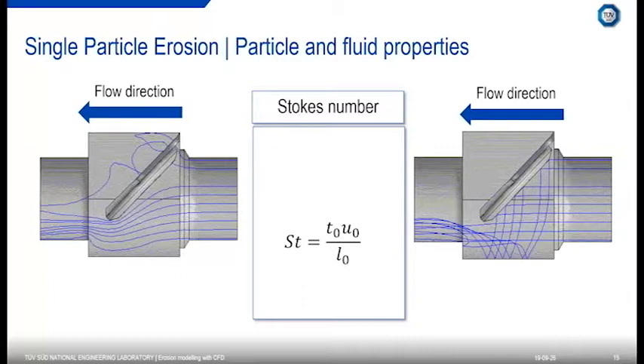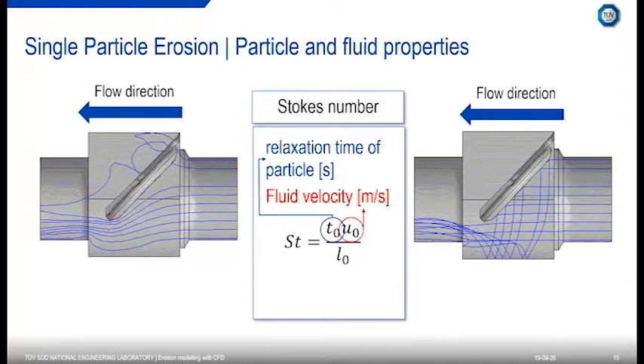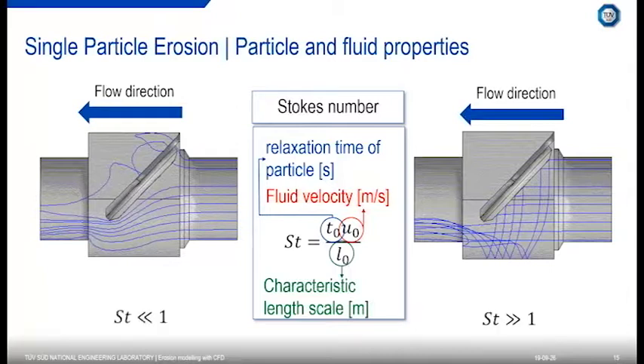So it's defined as the ratio of the characteristic time of the particle, given by the relaxation time, its fluid velocity, against its characteristic length scale, so that could be its diameter. Typically, what we see is when we have a Stokes number less than 1, it will typically follow the flow, whereas when we have larger Stokes numbers, it has high inertia and it will likely detach from the flow and impact the wall. And this is actually quite a useful tool when you're thinking about your actual design, whether or not erosion may or may not be a problem.